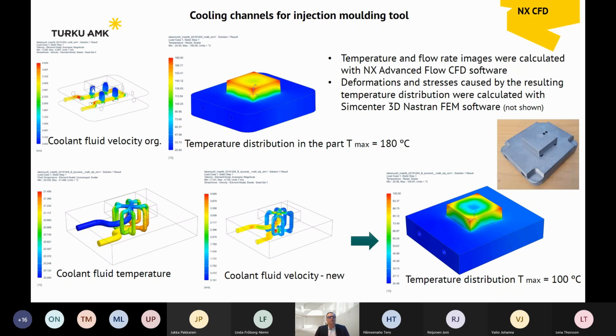So, as a simple example, there is an injection molding tool. In the top row, there is a conventional way to build coolant fluid channels. It's typically made by drilling or milling process, and geometry is quite limited. In this case, the maximum temperature was 180 degrees, and after the new design with more effective and smooth coolant channels, the temperature was lowered almost half to 100 Celsius.